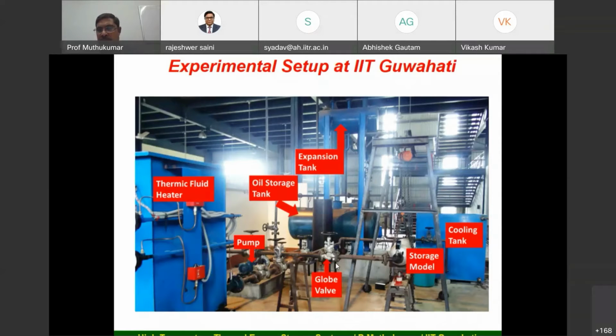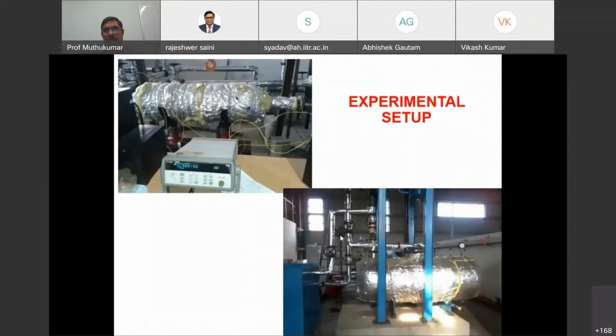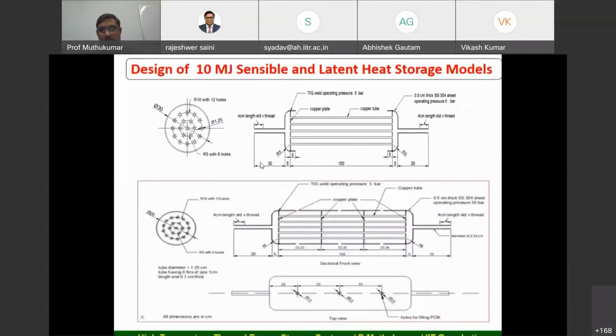For high temperature, we have another setup. This is the storage module that you can see here, and they are all connected with thermocouples and everything. So we tested here the concrete based one, cast iron based and cast steel based, several devices we have tested. And this is the concrete based one, and here we have the copper tubes as well as the stainless steel tubes and finned tubes. So these are the header, through which the fluid will be supplied. Then from the header, the fluid will be equally distributed to all the tubes. Then at the end it will come out.